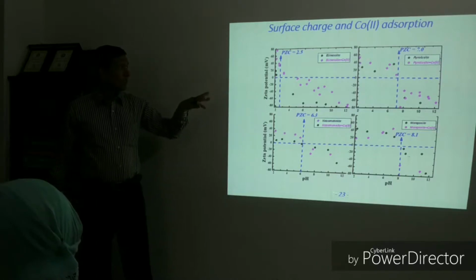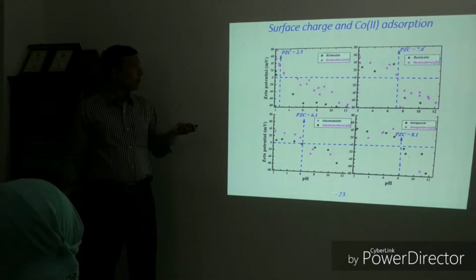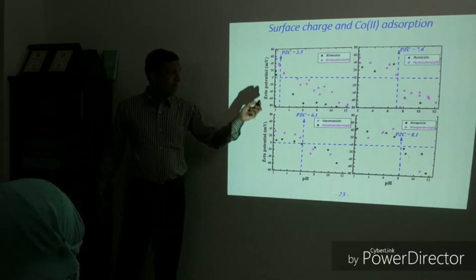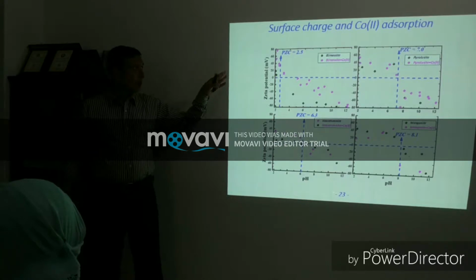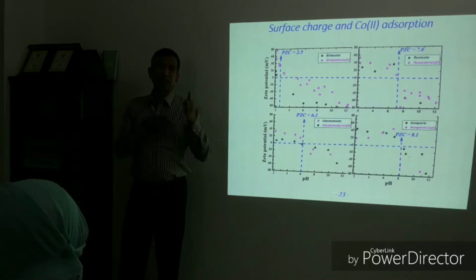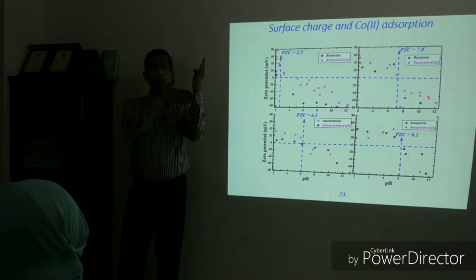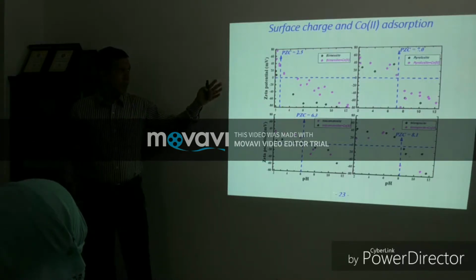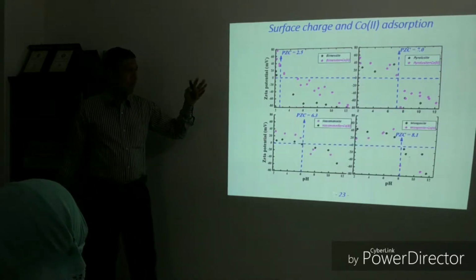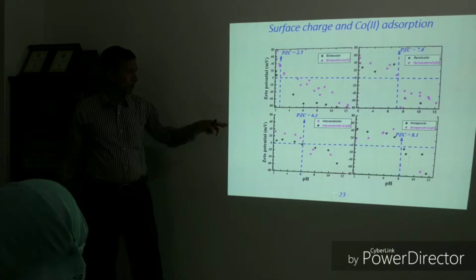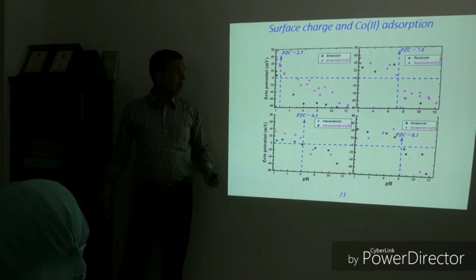Then surface charge and cobalt adsorption. If we see the figure, in case of birnessite and manganite, after adsorption of cobalt, the point of zero charge has been shifted. Based on literature, only in case of inner-sphere complexation, which is held at the zero plane or surface plane, the point of zero charge or surface charge is changed. On the other hand, outer-sphere complexation has no impact on surface charge, which occurred in case of hausmannite and pyrolusite.